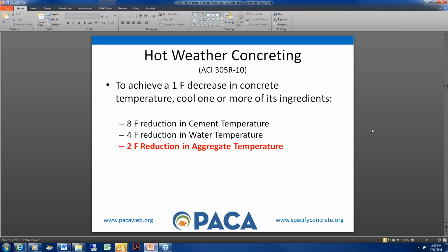It's supposed to be used as often as needed, and each manufacturer has their own spin on it. But as Pat alluded to, you do get crusting with retarder, and if you don't use the evaporation retarder, you will almost guaranteed have plastic shrinkage cracks. So everybody be forewarned, there's a lot of inherent risk using retarder. There's a lot of good about it, but there's a lot of inherent risk too. Like I said, it all kind of meshes together - hot weather, cracking, all these bad things happen, all these extremes.